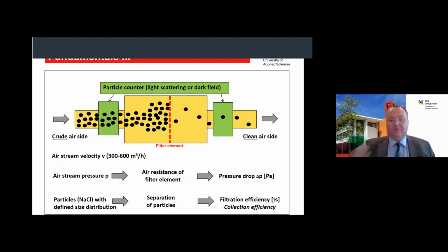to create a filter element with a high collection efficiency next to a low air resistance. And one important value to get an idea regarding the air resistance is the so-called pressure drop. Here on the crude air side, you have a certain pressure, and of course, due to the air resistance of the filter element, you have a certain drop of the pressure. That means the pressure here is lower than here, and the typical value you measure or give is the so-called pressure drop. Okay, there are also some other important parameters, clogging and so on, clogging time, but I cannot explain it here in the frame of this presentation. So let us go on.